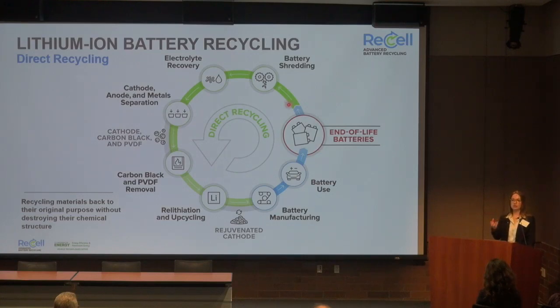We wash those battery shreds, and then we can recover our lithium hexafluorophosphate, which is the main salt component in your electrolyte, which we can then reuse. Then we have our cathode and anode still deposited on our current collecting foils of aluminum and copper, and we can use metallic separation to separate anode and cathode. We can then delaminate our cathode coating and then burn off our PVDF binder through a binder burn-off process. And then we have our cathode separated.